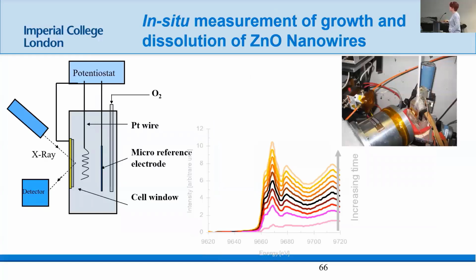So we started off by asking, how can we really, really sensibly measure the deposition rate? And we decided to use X-ray absorption spectroscopy. So this is an X-ray cell, which looks quite nice and well designed here in the schematic, and of course at the beamline, it looks like this Heath Robinson affair. But in this setup, we've got an electrochemical window, a very thin gold electrode, because we want our X-rays to come in and out, and then a normal three-electrode cell. And we drive this oxygen reduction reaction here and deposit things onto this surface.